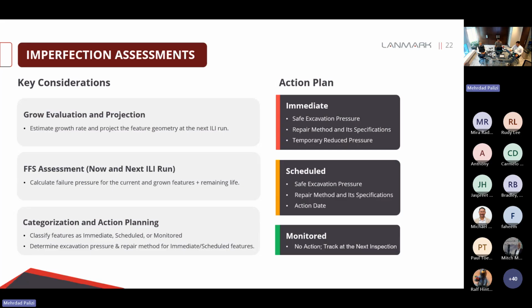Then we're going to perform FFS. This is going to be performed for both the current and projected condition of the features. Key outputs here include the failure pressure and remaining life. In the case of corrosion, this remaining life is because of wall thinning. And in the case of cracks and dents, it is going to be governed by fatigue failure.